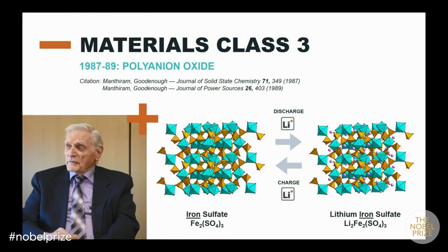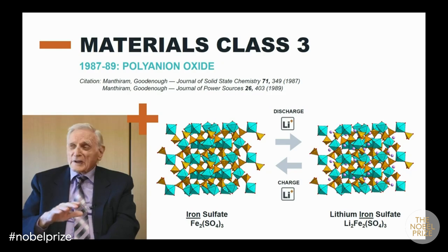There is a so-called inductive effect in which you get a very strong sulfur-oxygen bond in the sulfate, and that is able to reduce the energy of the iron 3 plus/iron 2 plus redox couple. I wanted to get a higher voltage, so I wanted to lower the energy of the iron 3 plus/iron 2 plus redox couple. And so you go to a sulfate. The sulfur has a strong sulfur-oxygen bond, and that then makes you have a more ionic bond with the iron, and lowers the energy of the iron 3 plus/2 plus couple and increases the voltage.